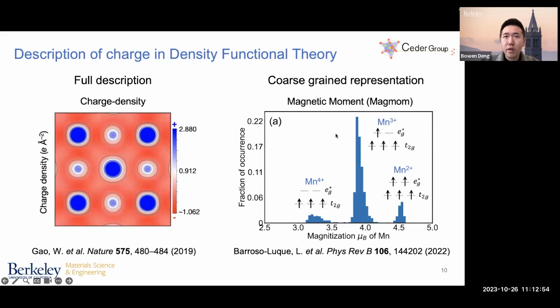So let's take a look at whether there's another way to represent this charge. Luckily, we have found that in spin polarized DFT calculations, the atom-wise magnetic moment, in short magmom, which derives from the difference in localized upspin and downspin electron densities, is actually a very good representation of coarse-grained atomic charge. For example, on the right plot, the three different peaks of magmoms ranging from 3.0 to 4.6 correspond to the distribution of manganese 4+, 3+, and 2+.